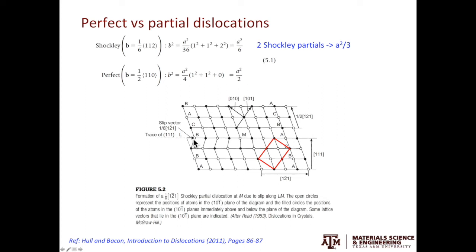Let's look at how locally Shockley partial dislocation interrupts the ABCABC stacking in the FCC metal. The letters started from ABC, then as if we are taking away A, then just putting BC here, then back to ABC. Let's have an even closer look. Starting from here, all the way down to this point, we have a perfect crystal. But starting from here, you have the first kink, then the second kink, then back to a perfect crystal again. For these kinks, since we see a mistake in the stacking, that's why it is called a stacking fault. Also, the atoms on the stacking fault have the twinning relationship with the perfect crystal, so stacking faults can also be viewed as a single atomic layer twin.